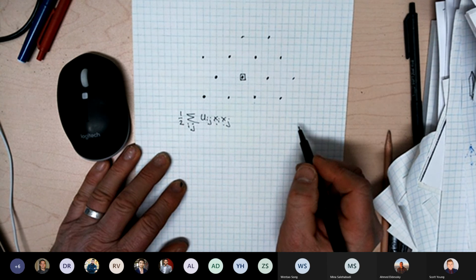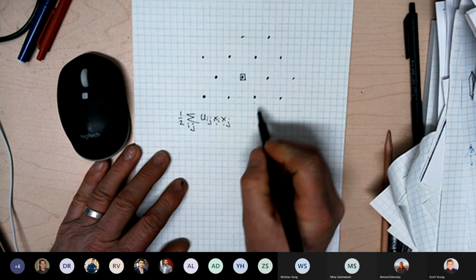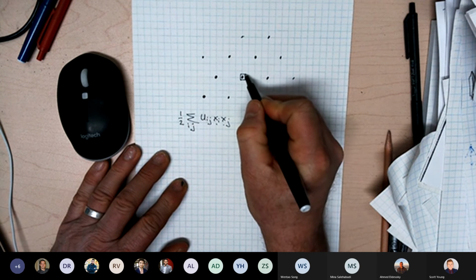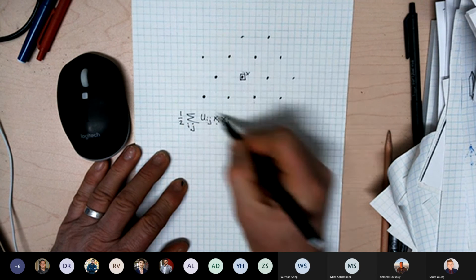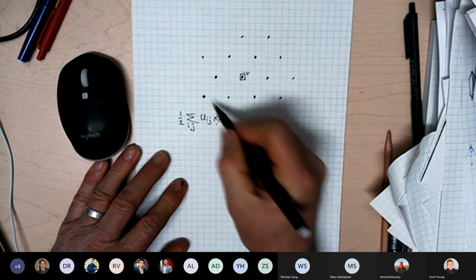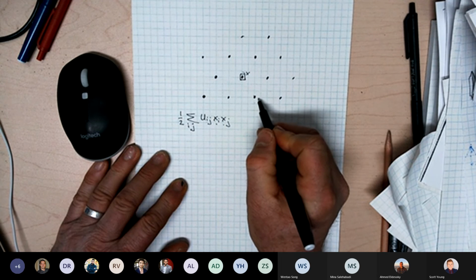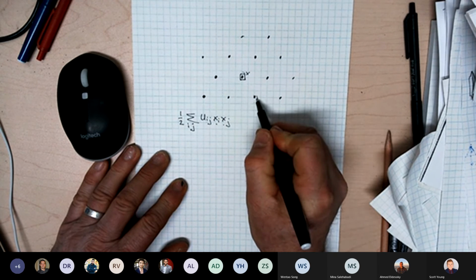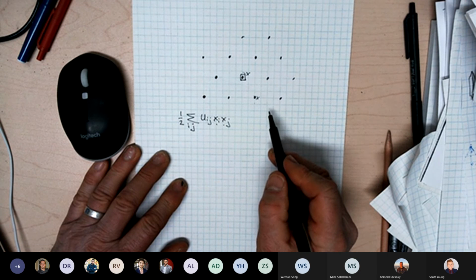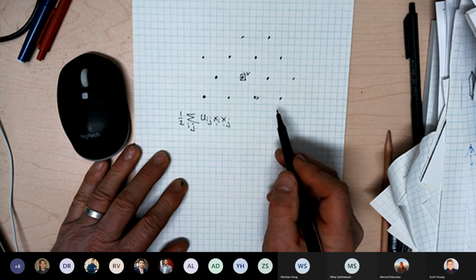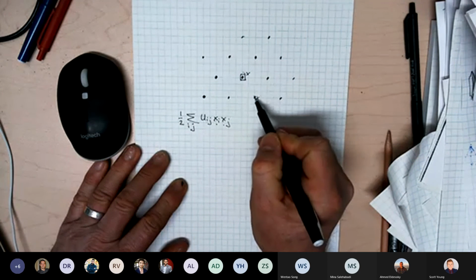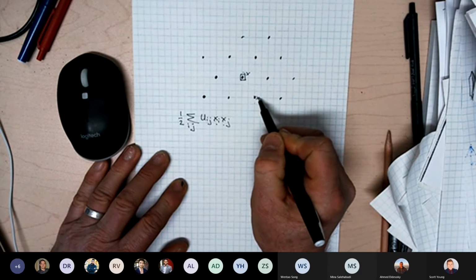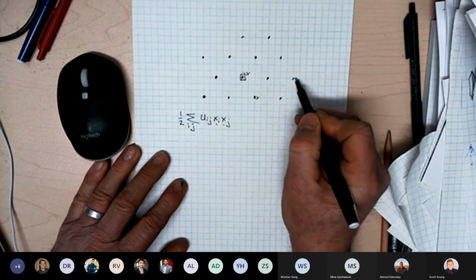And then when we make the mean field approximation, we just say, okay, look, the average occupation of this site is X, and the average occupation of all the other sites is also equal to the average occupation, it's also X. We basically said we can't distinguish where the lithium is anymore, because it could be over here.